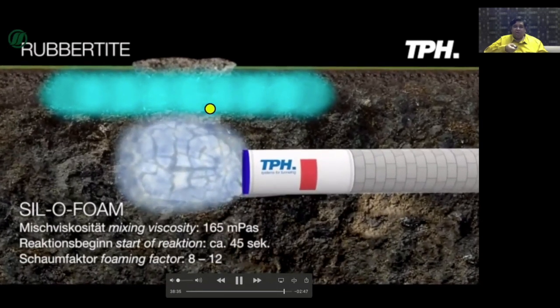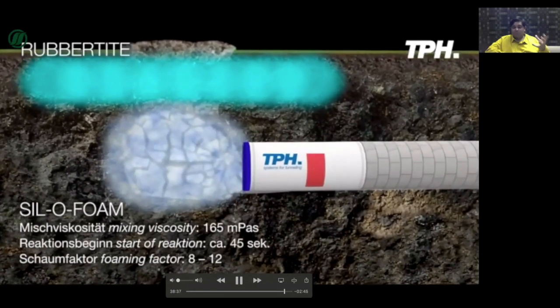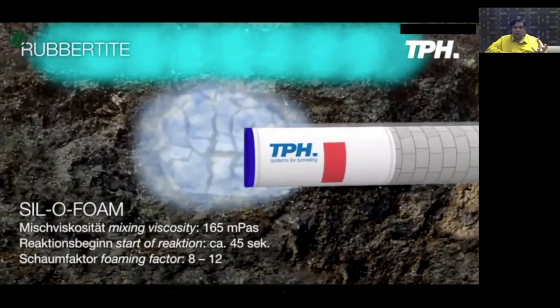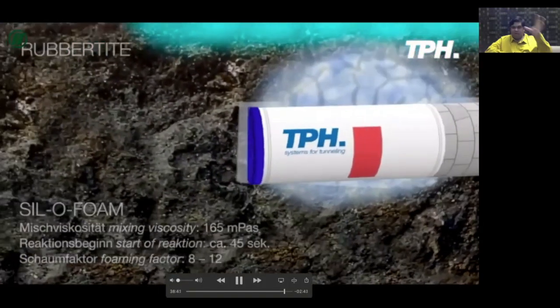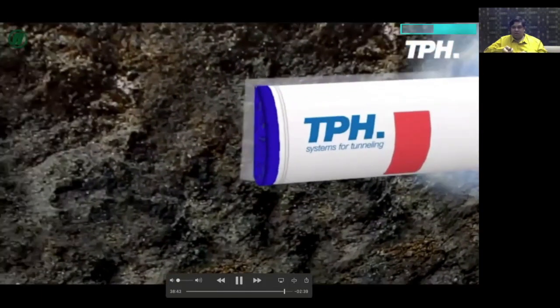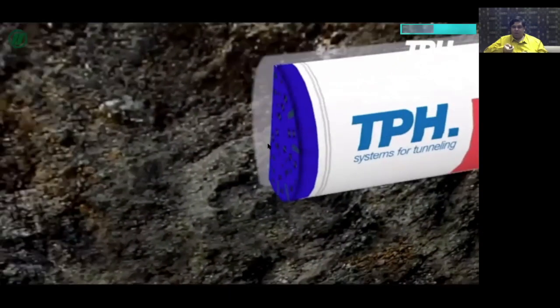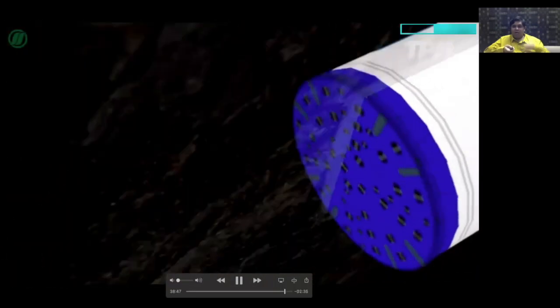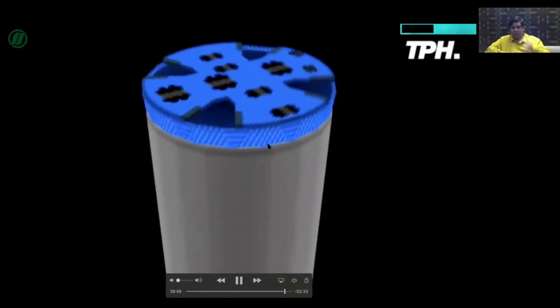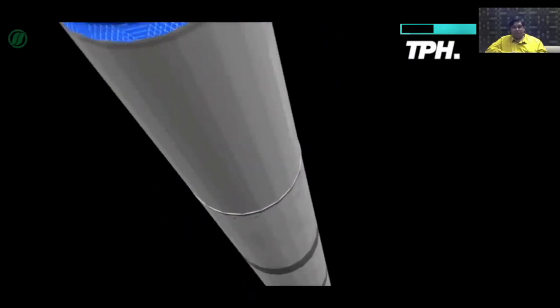And then what we do is with the fractured rock, you consolidate this fractured rock with a highly foaming, fast foaming silicate foam. So what it does, again, with a low viscosity, it can pretty much reach different areas of the rock. It can consolidate it, and the tunneling can proceed further very easily.